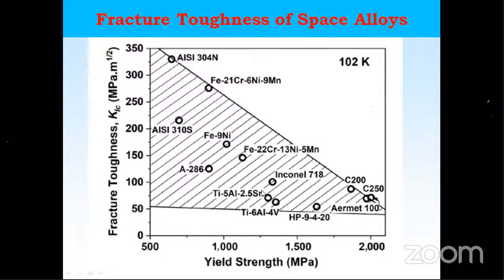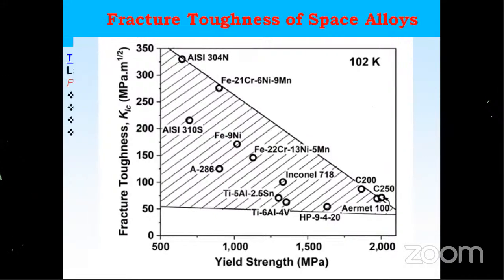And what I meant to say is that mostly all FCC materials show very, very high values. C200 and C250 are maraging steels, because of containing 18 nickel, they also show a good amount of toughness at low temperature. It doesn't mean that you do not use maraging steel for a low temperature application. It can be used, but it is a costly material. We have other materials available, so we don't use it.